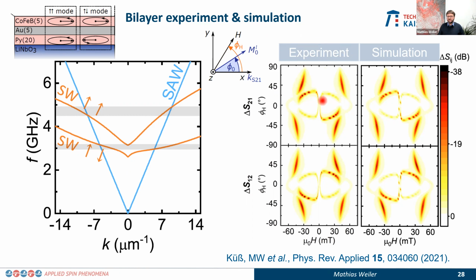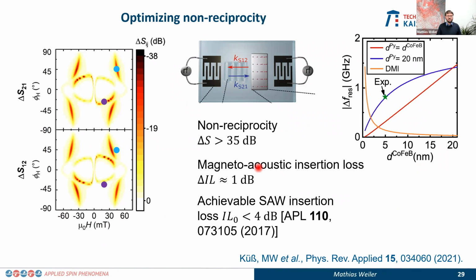We can see that we have our experimental data, and the simulation is basically also done using a purely analytical phenomenological model that we developed that just takes this spin wave dispersion into account. You can see that we have here full quantitative agreement between the observation and the model. And if you look now into the non-reciprocity, then we have to define an operating point. So we have to say if we want to use such a device, well, we could integrate some permanent magnet and thin film technique on such a device as well, and then say, okay, we get some orientation of this field and we get some value of the field, but that is something we can obviously not change once the device is made, right? So we could, for instance, operate it here at this light blue point or at this purple point over here. And then what we look at is microwave transmission from left to right versus microwave transmission down here from right to left. Right? And there is a very clear difference.